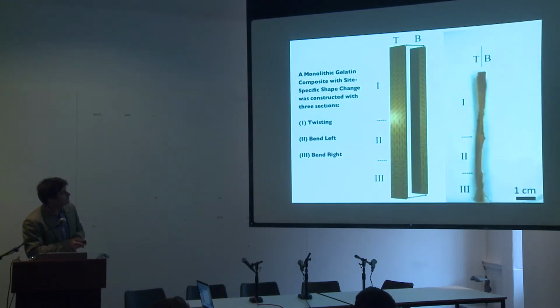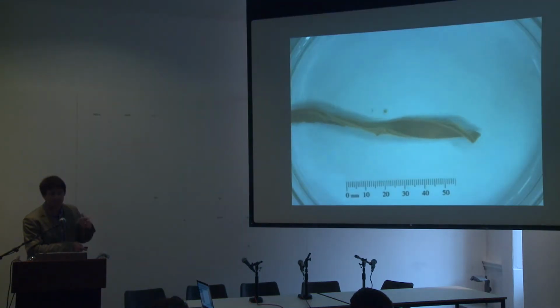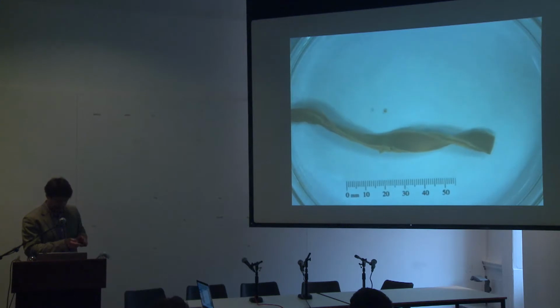The other possibility here is that you can program different regions of the material to undergo different shape change. So here we program this stripe, this part to twist, this to bend to the left, this to bend to the right. And if you eventually put them in water, you see that they will react as we've programmed.